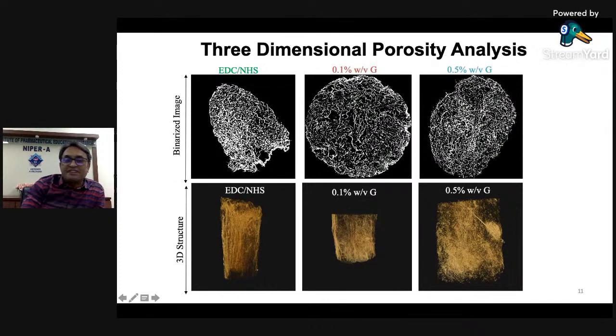Rather, the graphene probably is present as small islands. These are multi-layered graphene incorporated, and thus they form some aggregates. These aggregates are present which may act as small islands of conductivity.